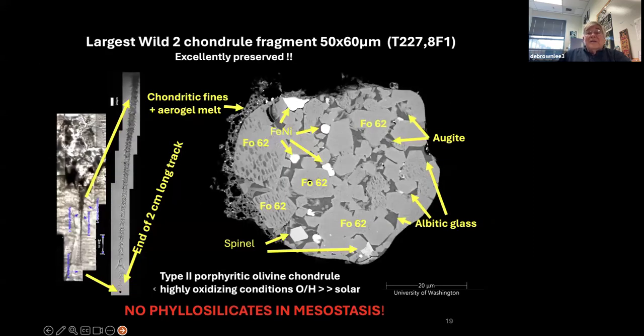This is the largest one we found. We worked on this just last year. It's 60 microns across, dominated by Fo 62 olivine, so it's pretty iron rich. There are little blades of augite, albitic composition glass, spinel, and around the fringes of it are chondritic fines, the stuff that normally ends up stuck up in the bulb, but those little vesicular melted stuff on the surface.